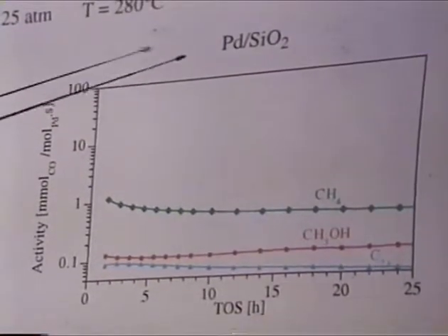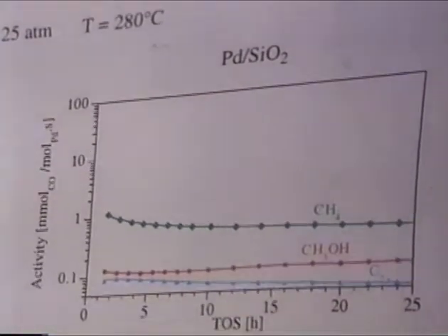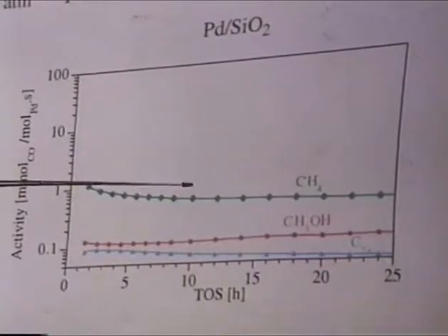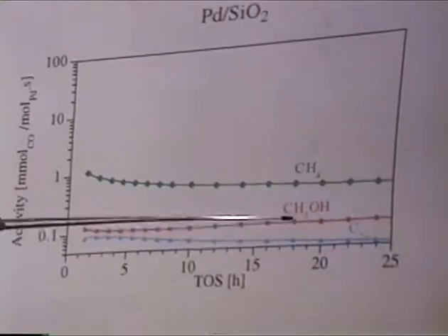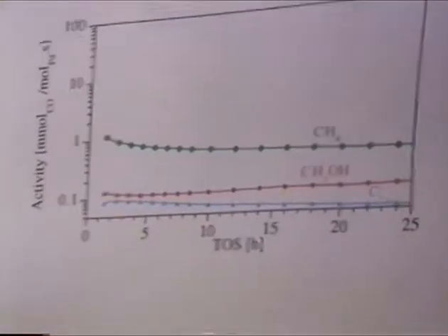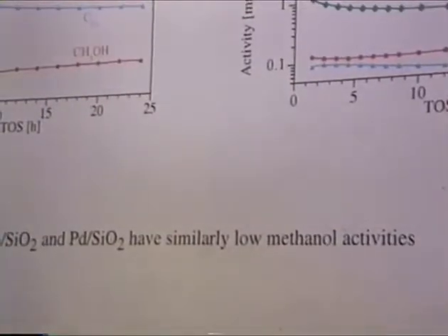Now the palladium on this very pure silica is a very bad catalyst. It's low in methane, it's of course much lower in the C2+, and it's also very low in the methanol. And actually I think that this little bit of methanol is just the last little bit of dirt which is still on this catalyst.